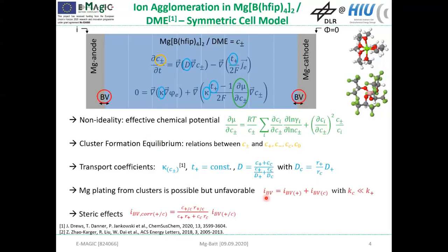For the conductivity and the transference number, we use the experimental data from our partner KIT, and the diffusion coefficient is described as a function of the cluster concentration. And finally, we use the Butler-Volmer approach to describe the kinetics at the interface, and thereby we assume that the plating from the clusters is in principle possible, but kinetically unfavorable. Moreover, the solvent anion is very bulky, and therefore it may hinder the plating reaction, which we also consider in our model.